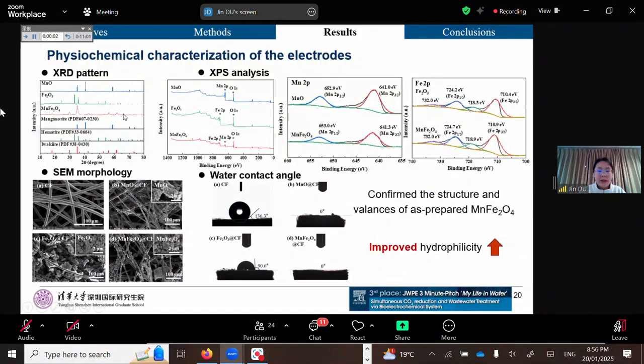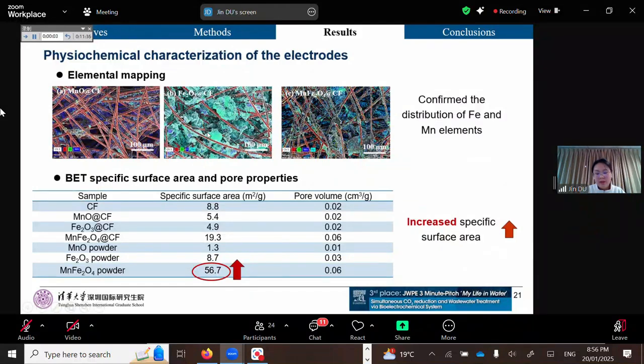We first performed the physicochemical analysis of the modified electrodes. The XRD and the XPS analysis confirmed the successful synthesis of the manganese ferrite with the expected chemical formula, crystalline structure, and valence states. The three modified electrodes generally exhibited improved hydrophilicity, indicating better biocompatibility. As you can see, elemental mapping revealed a uniform distribution of iron and manganese elements in the modified electrodes. Furthermore, the BET analysis indicated that the manganese ferrite modified cathode had 2.2 times the surface area of the unmodified carbon felt, also significantly higher than the modified cathode with manganese oxide and iron oxide.